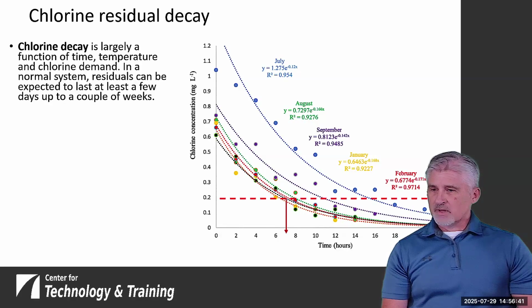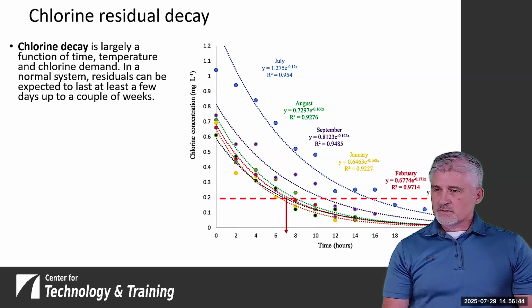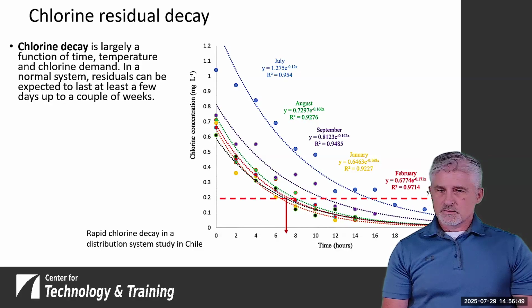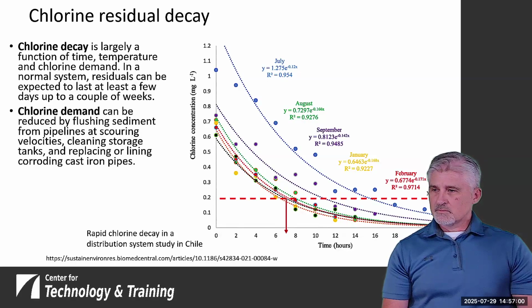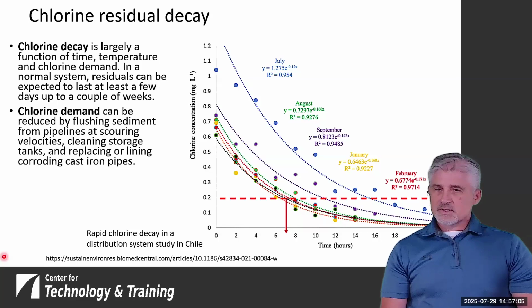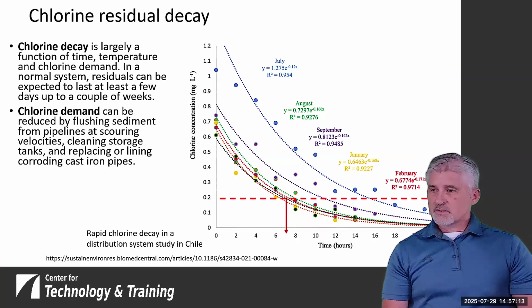So if we look at this spot, we have a chlorine residual of 0.2 after 7 hours. And then it drops off considerably as time goes on in this study in Chile. You can reduce the chlorine demand if you can get those sediments out of your pipes; you need to get it up to scouring velocities. If you clean storage tanks, it's surprising how much stuff can settle out in the bottom of a storage tank through time.